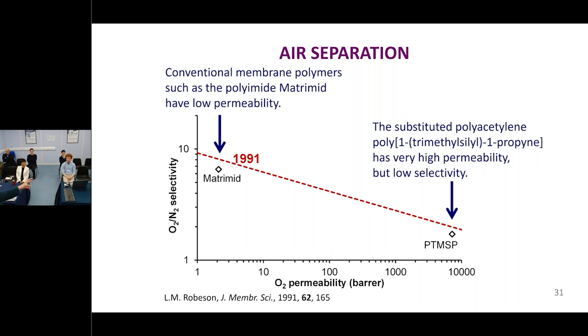What it does is it takes air and it throws away most of the oxygen to generate a nitrogen-rich inert gas. And that's then fed into the fuel tanks, so that as the fuel goes down, you don't get an explosive mixture above the fuel. That's been done since, quite a few years ago, a TWA flight exploded, and after that it was introduced onto most commercial aircraft. So air separation is a current application.